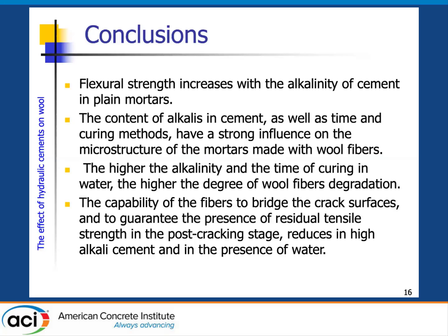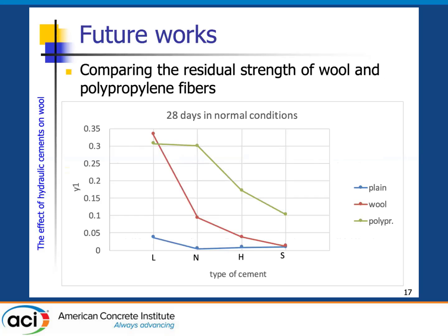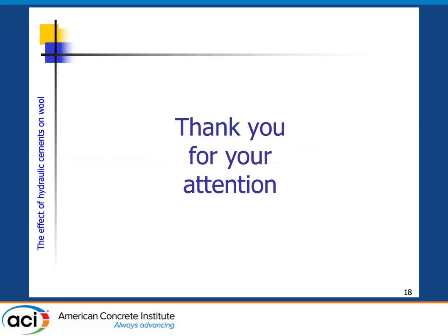and without water. I just want to show you this final slide, in which we compared the plain concrete, the wool reinforced concrete, the red one, and the polypropylene fiber reinforced concrete. As you can see, in low alkali cement, the performances of the wool and polypropylene are the same. If we increase the content of alkali, you have a decrement of the performances of wool, but pay attention, also the polypropylene fibers degrade in alkali environment. So thank you very much for your attention.